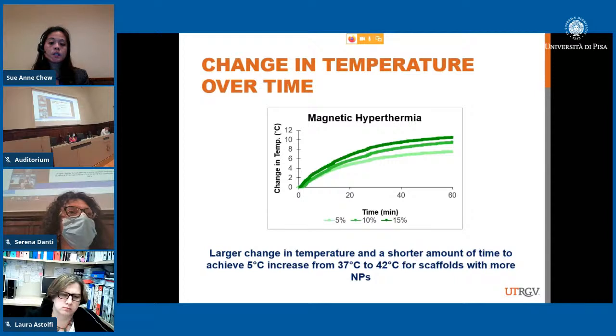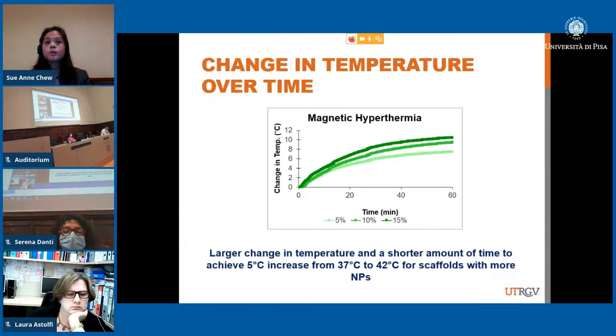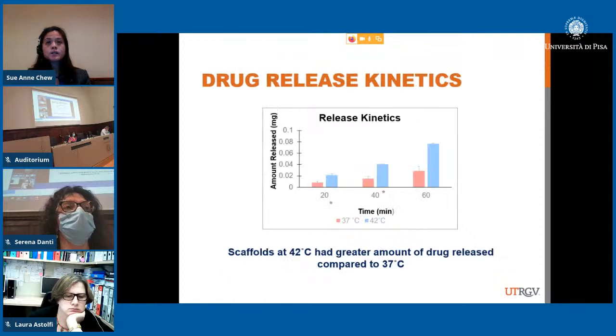So a change of 5 degrees Celsius. We were able to do that at a faster rate when we are using more iron oxide nanoparticle, as expected. We are targeting 42 degrees Celsius because that is what is usually used for hyperthermia in cancer, where they use heat to kill cells. So we were trying to make sure we remain in that temperature range, and to show that it's not toxic to the surrounding cells that are not cancerous.